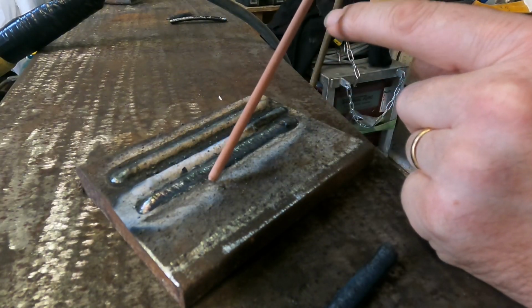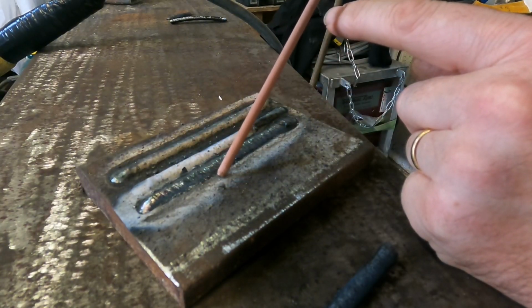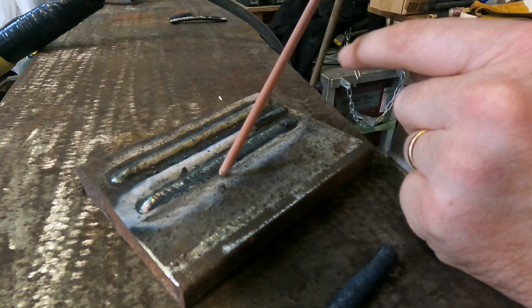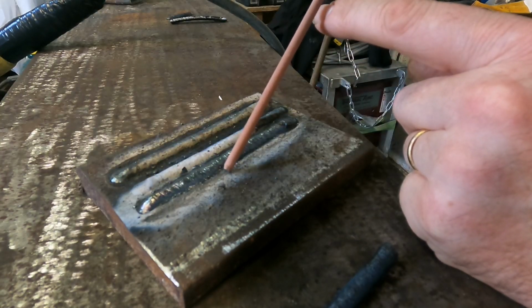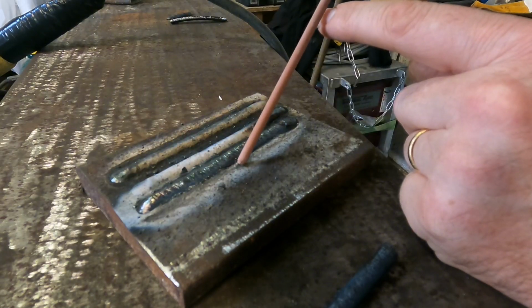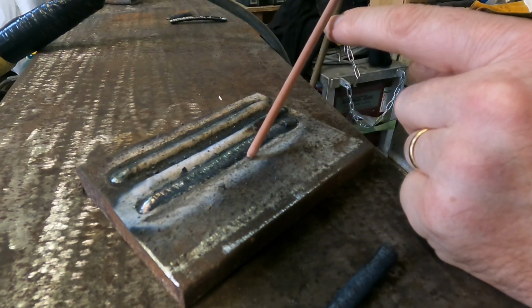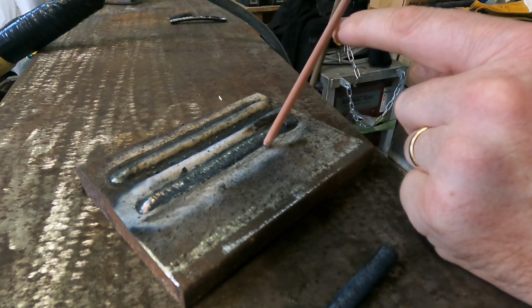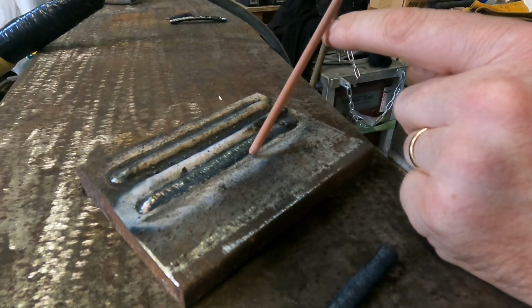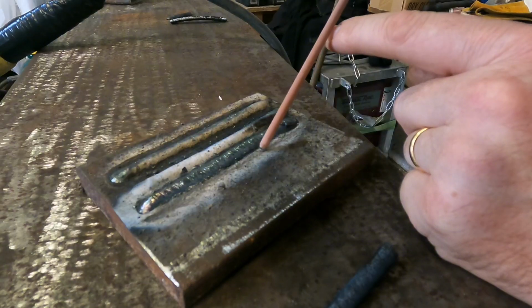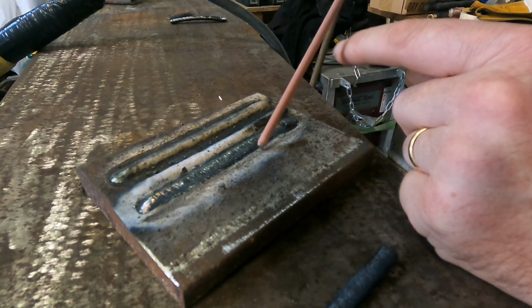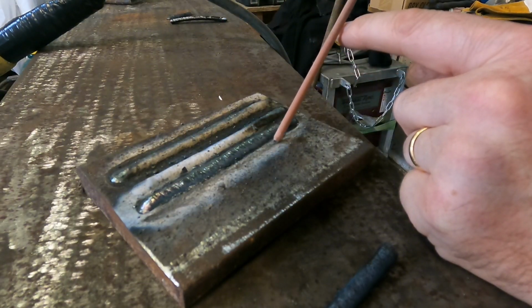So keep a good eye on your puddle and your rod, and also you have to keep an eye on your slag. If the slag gets in front of you, you're going to get what's called slag traps. So always drag a welding rod towards you at a slight angle like that. You never push a welding rod. If you push a welding rod, the slag will get trapped, and you'll end up with little holes in your welds. So always drag towards you as best you can.